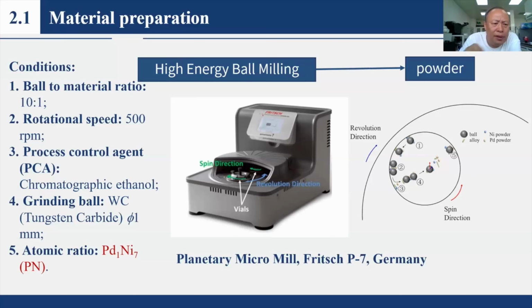The powders are milled using chromatographic ethanol, a liquid. Of course, it is cool milling and not in air. We use grinding balls of tungsten carbide, about 1 millimeter in diameter, and the rotation speed is 500 revolutions per minute. The ball to material ratio is about 10 to 1. Of course, other parameters were also used. I did not report them in detail here.